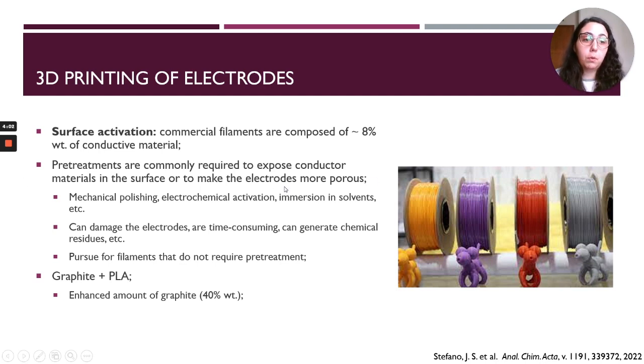or to make the electrodes more porous, and again, you will have more connection to the conductors. This can be done by mechanical polishing, by electrochemical activation, immersion in solvents, and a few other methods, electrochemical activation being very common. But these processes can damage the electrodes. They are time-consuming and can also generate chemical residues. So it's nice to avoid them if we can. So that's why literature is currently pursuing filaments that do not require any pretreatment.